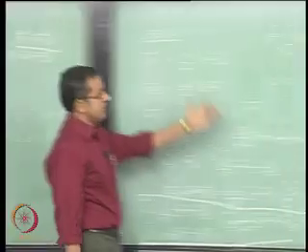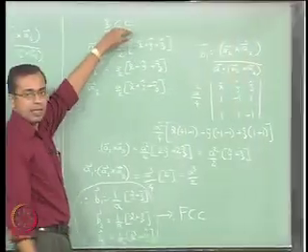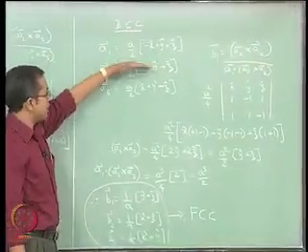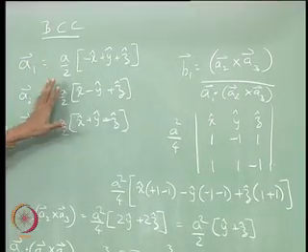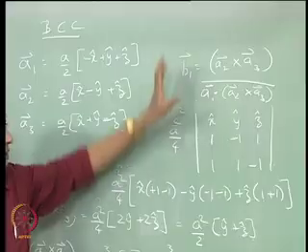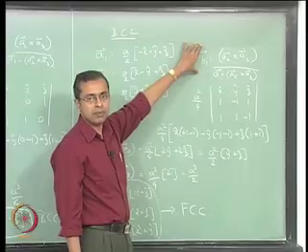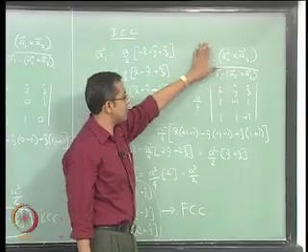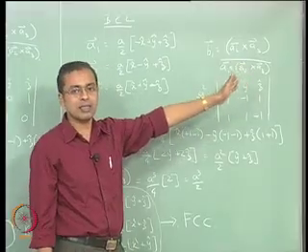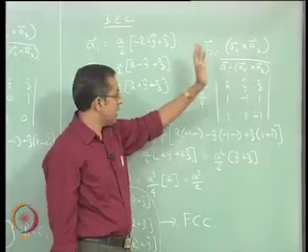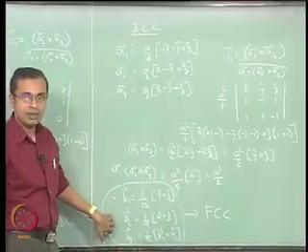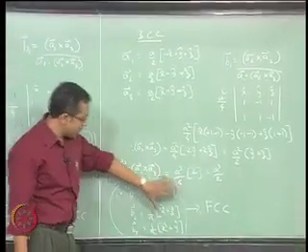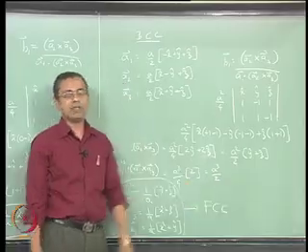Third thing we did: the other structure, which is body centered cubic. We took the characteristic vectors that represent body centered cubic atoms, and we looked at what would happen if we went through the standard procedure, enforcing the rules of the reciprocal lattice. We said that B1, B2, B3 have this relationship to A1, A2 and A3. If we enforce those relationships, we find that the vectors that result have a layout that is identical to face centered cubic.